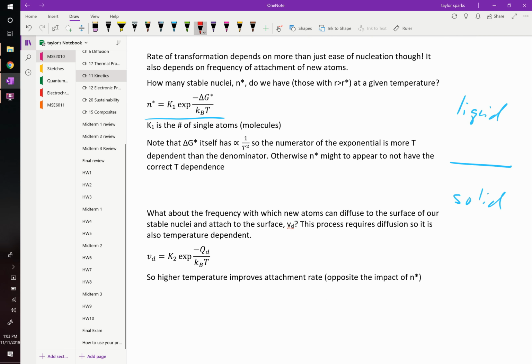What we know to be the case is that the further down we go, the more and more nuclei we should have because the activation energy gets smaller and the critical size also gets smaller. So it can't be that getting it higher and higher in temperature gives you more nuclei. And the reason why it doesn't is because delta G itself depends on temperature, right? So that's why that makes sense. It has its own temperature dependence built into it. It's not a constant. It depends on temperature, okay?